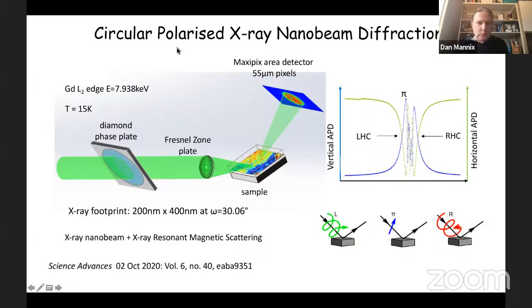Our setup that we used on ID1 combined the X-ray nanobeam and resonant X-ray scattering. This is what the setup was like. We had a phase plate. In fact, we borrowed the phase plate from the XMaS beamline and brought it to ID1. We worked at the gadolinium edge, as I said before. We could cool the sample down to 15 Kelvin. And then we started to use strongly focusing optics. Using this zone plate, we get down to a beam spot of about 200 by 400 nanometers, cooling down the sample and translating it in the beam and measuring the response on a 2D detector. This is the response of the phase plate giving circular polarized light. So using different angles of the phase plate, we can get either left or right circular polarized, or some pi polarized light incident onto our sample.